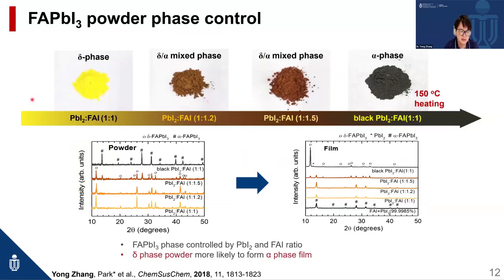Using this method, we can also apply it to FAPbI3 perovskite crystal powders. We can synthesize the delta phase, alpha-delta mixed phase, and also the alpha phase perovskite powders, as well as different kinds of phase perovskite film.